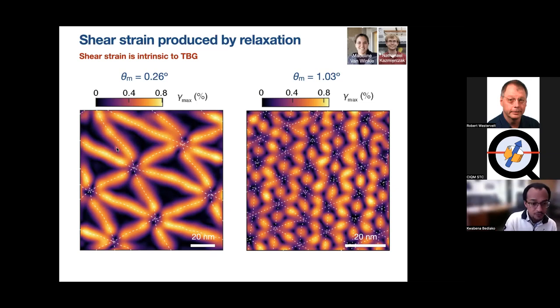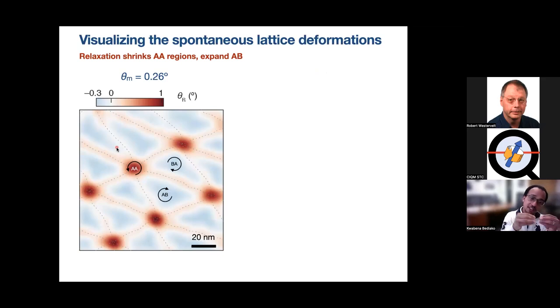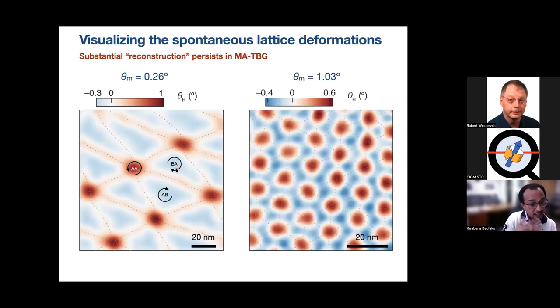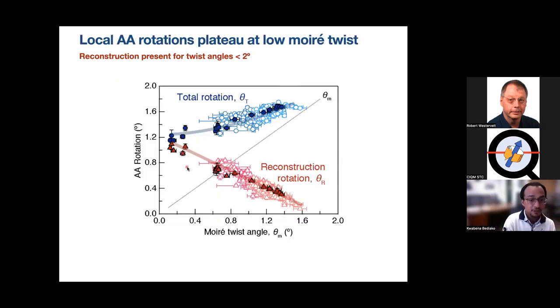And this is an intrinsic strain that is always going to be present, intrinsic to the graphene. But we can go a step further, because at each point, we take our displacement vector, we take its gradient, and we end up with a strain tensor at each pixel. And that's what allows us to get the strain at each pixel. But that tensor can also be manipulated in a way to extract information about local rotations that are present in the sample. And so we can actually measure directly the relaxation deformations, the relaxation rotations that have taken place. And so we see direct experimental evidence then of the positive rotation in the AA regions and the negative rotation in the BA region. And we can actually put numbers on that from the experiment. And this is present at all angles. So we can actually see that the rotations are present. We can map these local AA rotations as a function of the moiré twist angle.